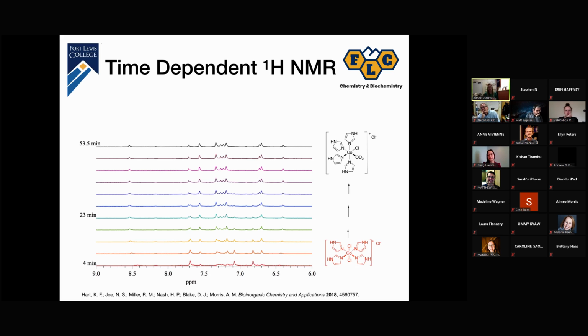And so one of the things you notice is that that high degree of symmetry becomes broken very quickly. And that there's definitely lability and ligand substitution happening in D2O. And we predicted that the species you end up with in the end would involve several ligand bond breaking and remaking steps to end up with a no longer symmetric cobalt 3 complex that now has one chloro ligand and one water, or more likely in this case, D2O ligand attached because of how much D2O would be in there. And so this is what we think is happening over time in the presence of water.